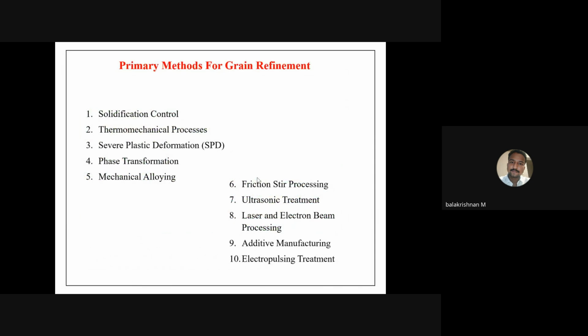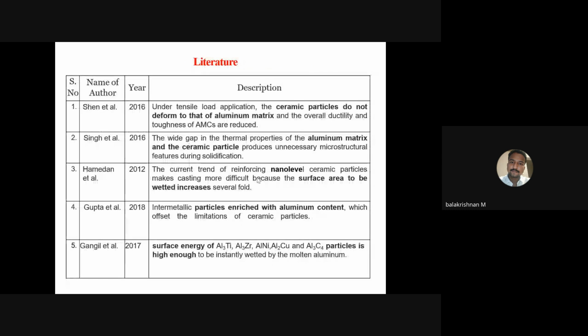Then, primary methods for grain refinement. Whenever we are looking for secondary processing, these are the primary stage to make fine refinement in the property of the material. Whenever we select the process parameters perfectly in the initial stage, we can attain it through the primary methods itself. Some of the methods are solidification control, thermomechanical process, severe plastic deformation, phase transformation, mechanical alloying, then friction stir process, ultrasonic, that is from heat, vibration and laser. We can improve the grain refinement. If it is not possible, again we have to go for secondary process.